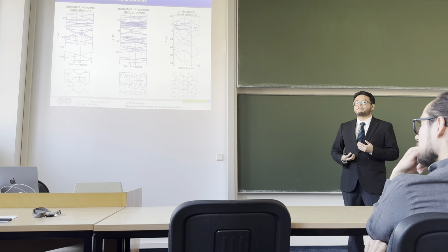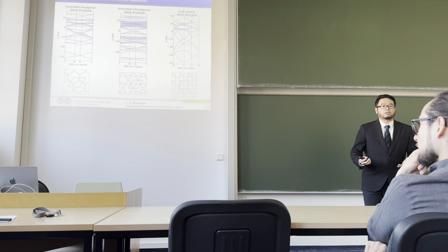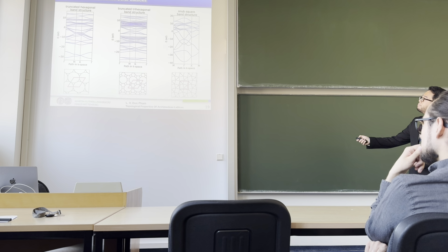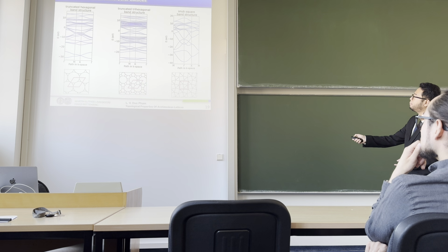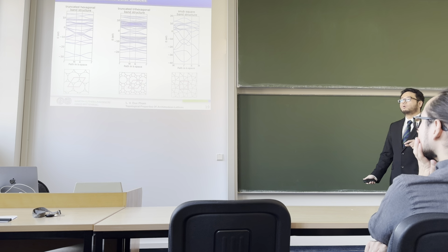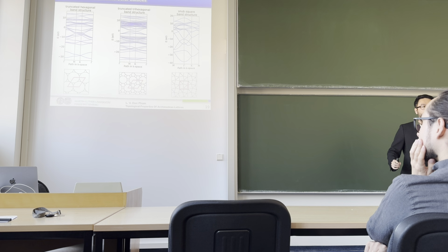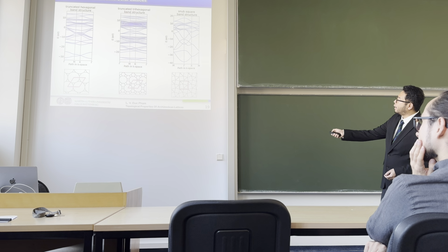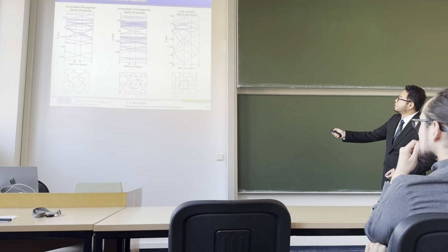And here are some more band structures of the other lattices, and we obtain these by using the graphene parameters, and graphene is a conducting material. Most of our lattices, besides the gap between the S band block and P band block, have no other fundamental gaps throughout the Brillouin zone inside the P block. So for example, this is the case for the snub square lattice. The band structure doesn't have any fundamental gap inside this block.